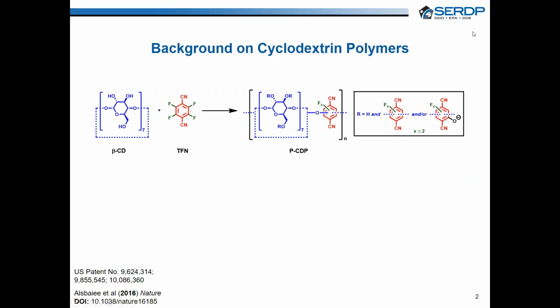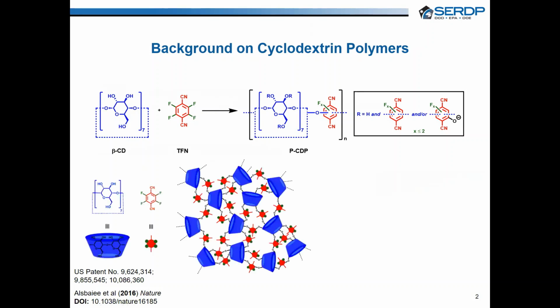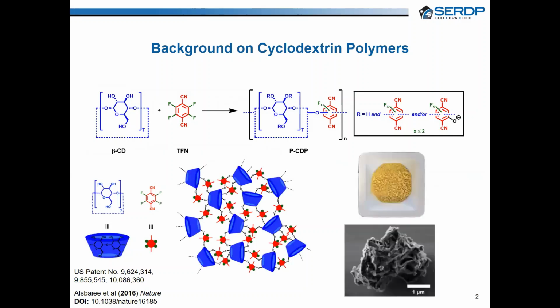Our novel adsorbents are polymers of cyclodextrins, in which the cyclodextrins are cross-linked by a rigid aromatic compound to generate high surface area polymers with permanent mesoporosity. An example of the synthesis reaction is shown here at the top of this slide. The resulting polymer network is shown as a cartoon on the left of the slide and in its as synthesized morphology in the images on the right. And you can see the as synthesized polymer is a yellowish powder of irregular particle size.